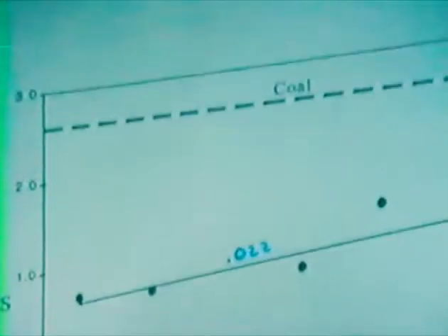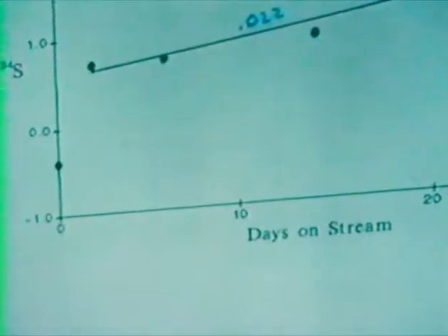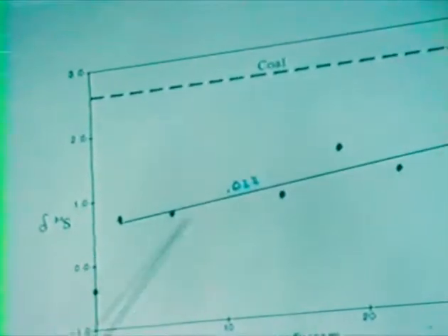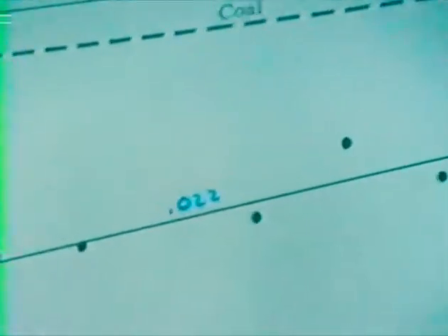When we received the analysis of the sulfur 34 values, this plot shows them for the second reactor, because again we did have more data points for that. It ran longer in the batch deactivation mode. What we see when we compare the pre-sulfided catalyst with the feed coal values and then the spent catalyst on stream are basically two rates of sulfur exchange.